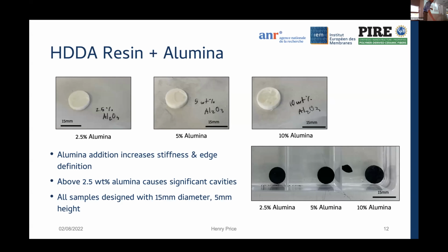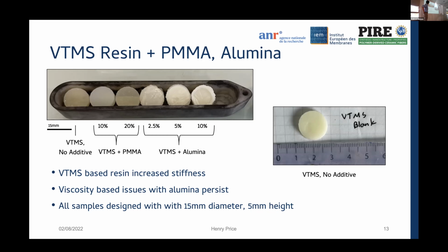Now, I'm going to switch to the other resin chemistry system, this VTMS. Again, this is a qualitative evaluation. I did not conduct any mechanical testing, but they increased the stiffness of these prints. However, the viscosity issues with the printing of higher weight percentages of alumina persisted. You can see there's a cavity there. It revealed that we should stick to these lower weight percentages.